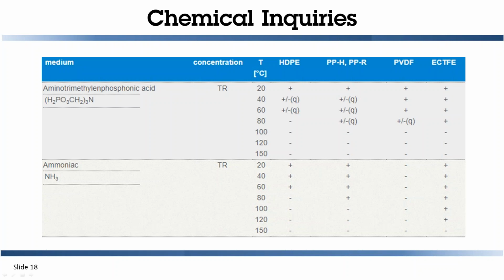When it comes to chemical resistance, it's very important to know where you're getting your information from. There are dozens of compatibility guides out there online. I always recommend asking the specific manufacturer for their guide. As you can see at the first chemical listed, depending on the temperature, there are several options for materials. Remembering that price generally increases from polyethylene to polypropylene to PVDF and ECTFE. If your application is ambient temperature here, you might be better off with HDPE. If you have a higher temperature range, you're going to be limited to PVDF or ECTFE.